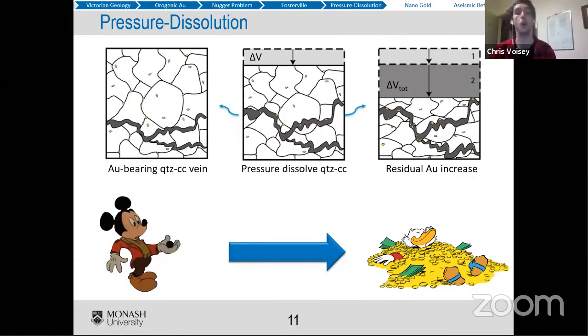So the way the story goes to this point was that you could have little bits of gold living in a quartz vein. You then put the whole thing under compression, which it normally is anyway, until it fails, and then it opens up a little bit and keeps going. When it is shortening, you can pressure dissolve quartz and carbonate material, which is the vein material. It's the gangue, the stuff we don't want. Gold remains insoluble, and it gets caught along these pressure dissolution seams, because you leave it behind; it's not soluble under pressure. It's actually quite malleable. And then you can enrich your gold vein by taking the stuff that's not gold out of it. You can take something that's maybe an anomaly, but not necessarily gold rich, and by removing the bits that aren't gold, you can make it gold rich. So you're almost mini mining your vein in situ naturally.